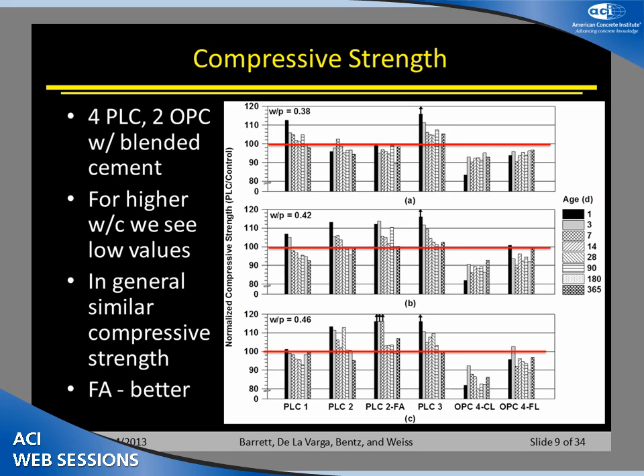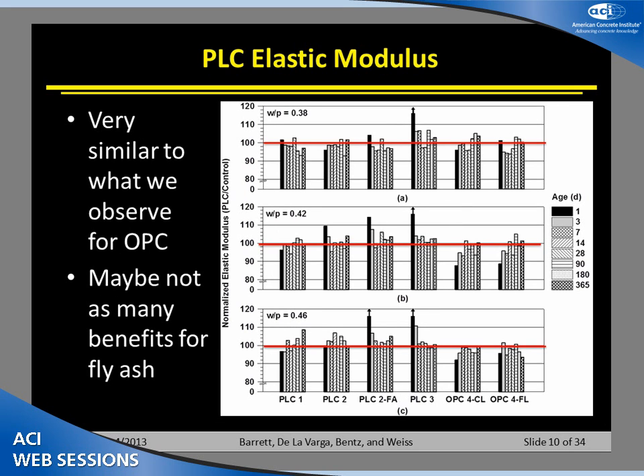When we've got fly ash in the system, we typically see a slight increase or a slight kick up in the system. And then the last 2 columns we look at over here are, instead of an equivalent system, when we're adding limestone to the system, just adding it, not intergrinding it. And typically we can see that effect that we talked about before, that dilution, where when we replace 10% of the cement with limestone, we'll notice that the properties drop so that we get 85 or 90% of the overall strength.